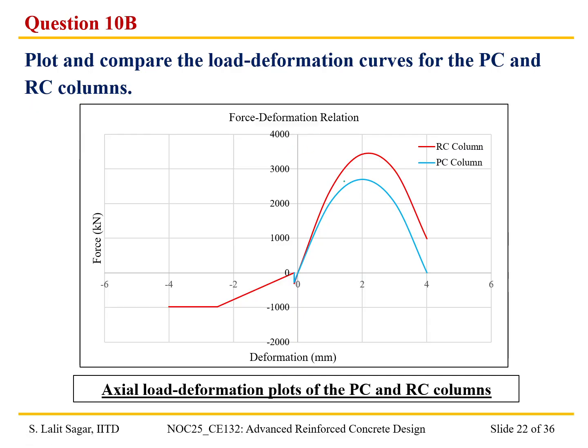insertion of the steel rebars increases the stiffness, the compressive stiffness, the tensile stiffness, and the peak compressive strength, the peak tensile strength, and essentially the behavior is more ductile when compared to the plain concrete column. Which is why providing the reinforcing steel is significant in order to enhance the mechanical properties of the concrete systems.